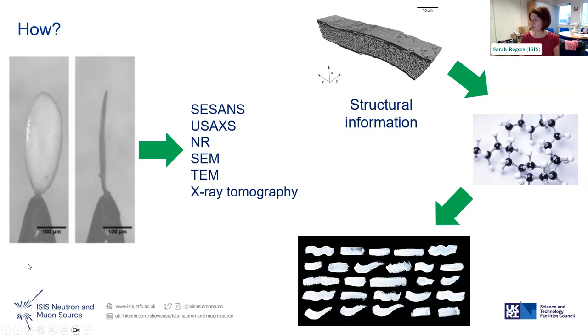So they've done a combination of the spin echo SANS, USAXS, which is basically ultra small angle X-ray scattering, and reflectivity. They've done obviously electron microscopy, SEM and TEM, as well as X-ray tomography, which is what that little thing they're going to spin around and have a look at, which has then gained them a lot of structural information. So they've then been able to work out what molecules they need to make such a structure. And then hopefully that will lead to the design of new paints.